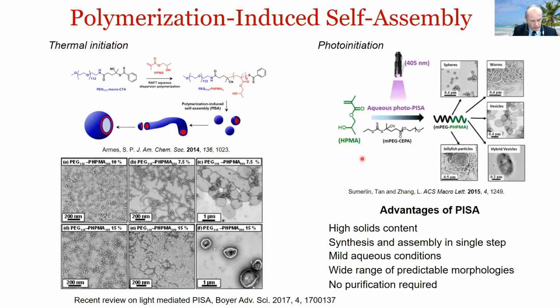Just to highlight some of the really nice work that's been done in this area, Steve Armes has done some really lovely work where in this case he takes a PEG macro CTA and then through RAFT polymerizes HPMA to form this block, and through this polymerization-induced self-assembly process you can see here the range of morphologies that he can produce. And then more recently there's been some really nice work from Sumerlin, Tan and Zhang, who showed that you could use aqueous photoPISA, so we're now starting to be able to use very mild polymerization conditions, in this case just 405 nanometer light, to enable this polymerization and then indeed create similarly complex morphologies.